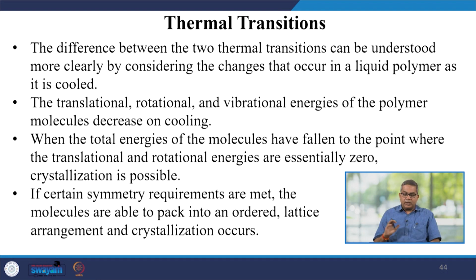The difference between the two thermal transitions can be explained more clearly by considering the changes that occur in a liquid polymer as it is cooled. So, you heat a liquid polymer, polyethylene, and then observe the behavior during cooling. The translational, rotational, and vibrational energies of the polymer molecule decrease on cooling, until the total energies of the molecule have fallen to the point where the translational and rotational energies are essentially zero. Crystallization is then possible. If certain symmetry requirements are met, the molecules are able to pack into an ordered lattice arrangement and crystallization occurs.